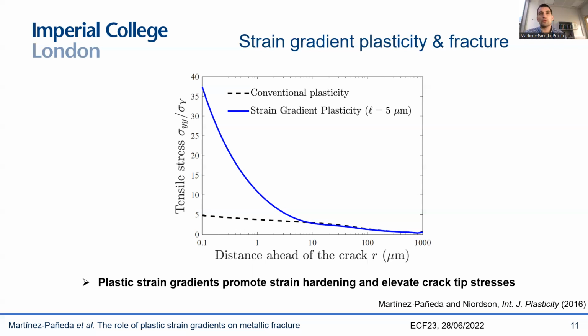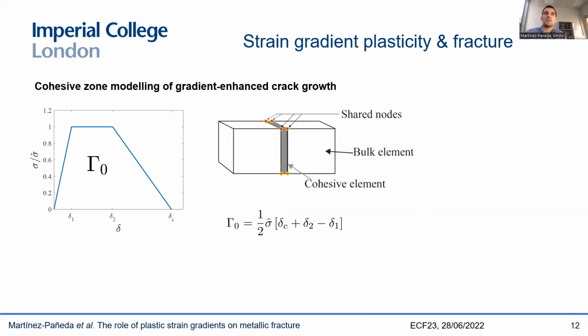So we tried to use this hypothesis. We said, okay, maybe this elevation in stress that results from GNDs, from plastic strain gradients, is what is driving those brittle fracture processes. And we looked into this by doing a cohesive zone analysis. So we tried to simulate a crack propagation. This is inspired by a classic paper by Tvergaard and Hutchinson in JMPS 1992, where they use cohesive zone elements and conventional von Mises plasticity to predict crack growth resistance curves, R curves, to predict the crack growth resistance associated with plasticity. And the idea is quite simple.